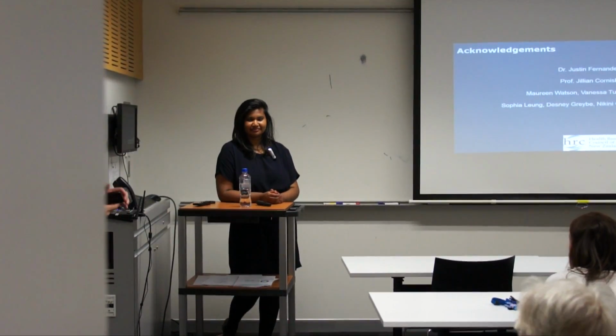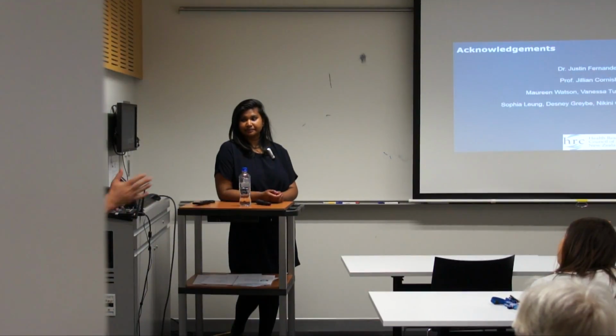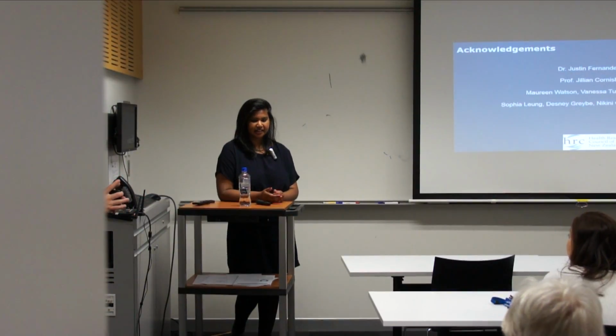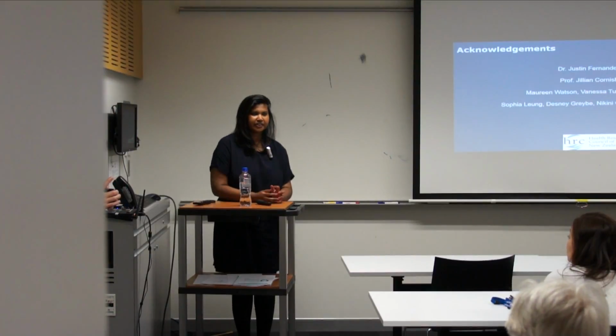I think she found something very interesting with 3-point bending. Well, you found something quite interesting with the 3-point bending, how different they were to the others. Yeah, so they ended up failing at a much lower load compared to nano indentation and micro indentation, and then we couldn't really explain it, and we ended up finding in the literature that mice femurs shouldn't really be tested by 3-point bending. They twist a lot during the test, and it's just not a good source of material properties.